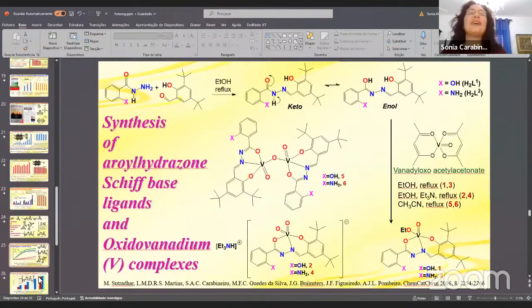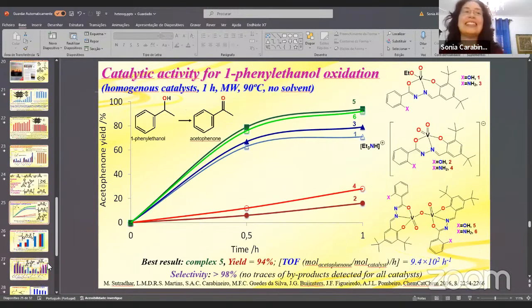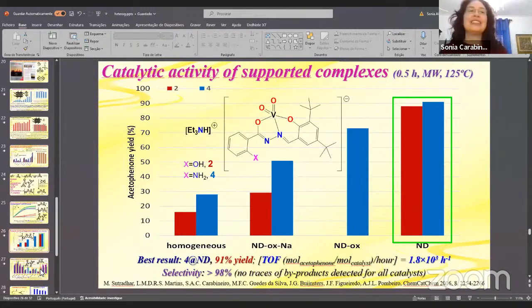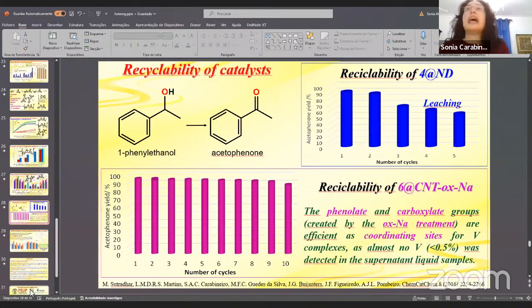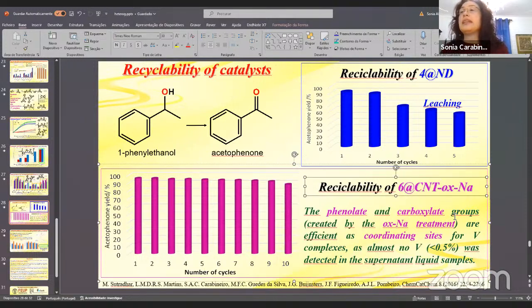Well, we also do not know the reason here. We just found a much higher leaching. The best result was obtained with nanodiamonds that were not functionalized, so it was easy for the complex to go away. But with the oxidized sample, these phenolate and carboxylate groups could anchor the metal more easily, so it was easier to recycle.